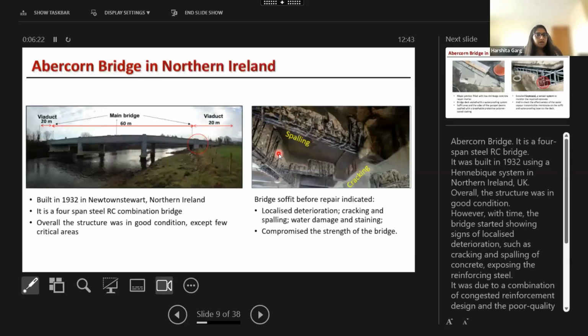So Abercorn Bridge was built in 1932 in Northern Ireland. It's a four-span steel and reinforced concrete combination bridge. So overall, this bridge was in good condition, but over time, it started to show signs of some localized deterioration, such as cracking and spalling of concrete, which exposed the reinforcing steel. There was also evidence of water damage and staining from all the exposed areas, which led to the compromising of the strength of the bridge.